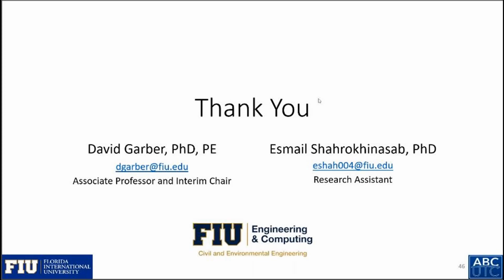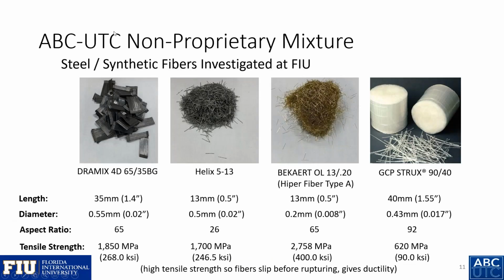So with the Dramix fibers, we found that in our mixes, those fibers would settle and clump. So we used viscosity modifying admixtures to stabilize those fibers. And then, yeah, we saw some floating with the lighter fibers as well. But with the VMAs, we were able to stabilize the fibers in the matrix.